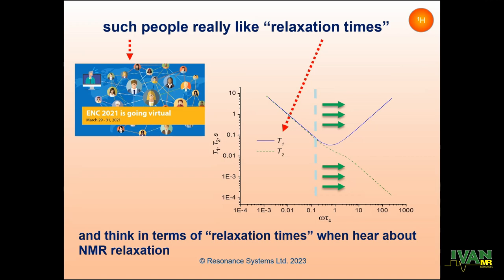Then, from our experience, we are installing instruments and talking to customers who have quite a good education in physics or chemistry, and they are somehow familiar with NMR. And when we come to the topic of time domain NMR, everybody is saying, I want to measure relaxation times, I want to know relaxation times, and everything is dancing around relaxation times. So the main impression of most classical NMR users, not dedicated NMR users, is that they are talking about relaxation times. Okay, relaxation time is something really interesting, especially when you are implementing the quite simplified approach of Bloembergen-Purcell-Pound theory. So you have some dependence of your relaxation times on the frequency and the mobility of your molecules. And then you can get some quite valuable information.